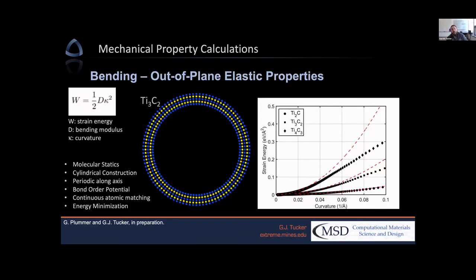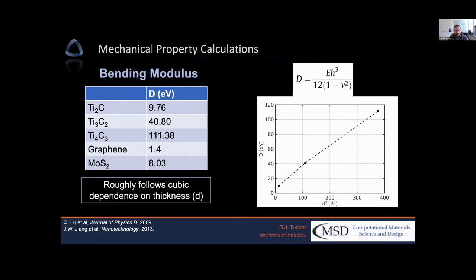The next thing we want to do is look at the out-of-plane elastic properties such as bending. And so here we just took one of these MXenes and bent it at different curvature values and calculated the strain energy for those, and then fit that to a continuum function to calculate that out-of-plane elastic bending modulus value D. And if we were to do that for different systems, what we end up seeing here is that the 3 different MXene chemistries that we looked at all have much higher bending modulus values than both graphene and molybdenum disulfide. And when we actually plot these values on a curve, we see that it roughly follows the cubic dependence on the thickness of the MXene, which it should. But to verify that actually was a very important step here.